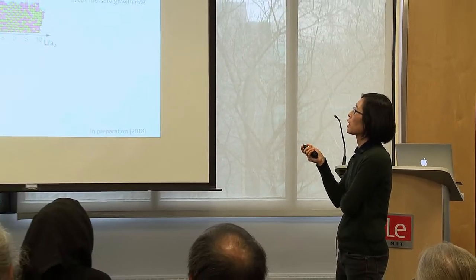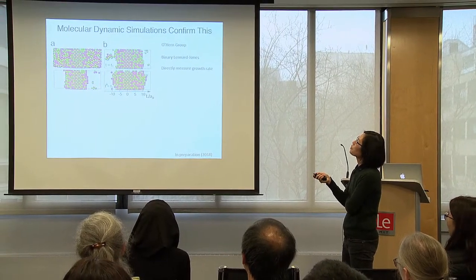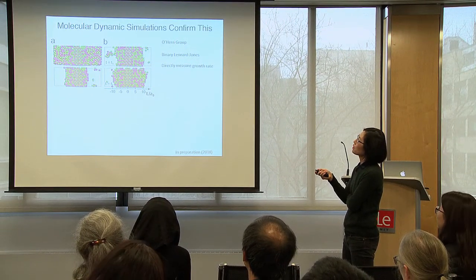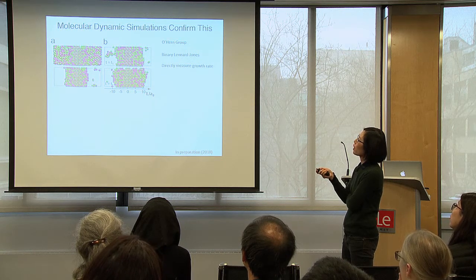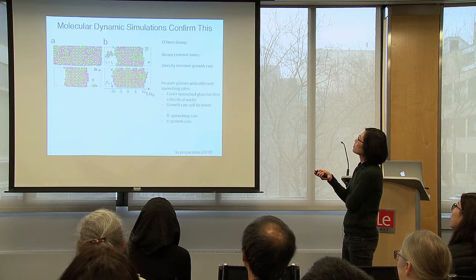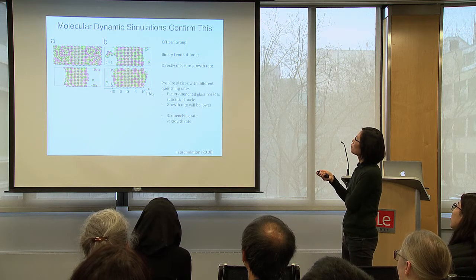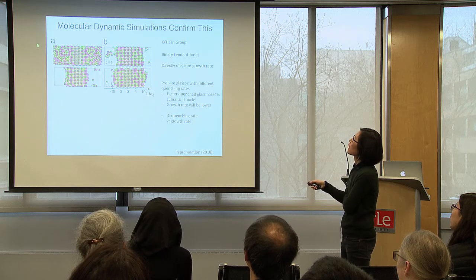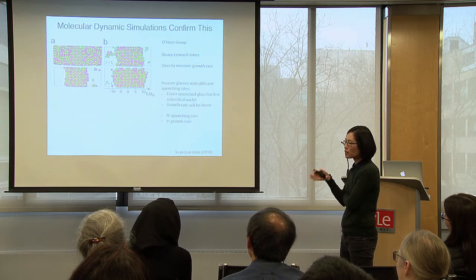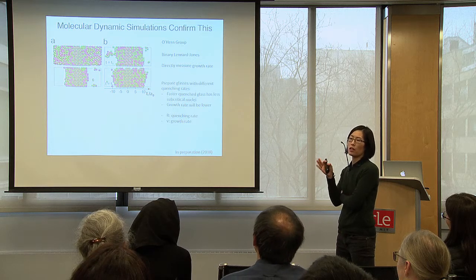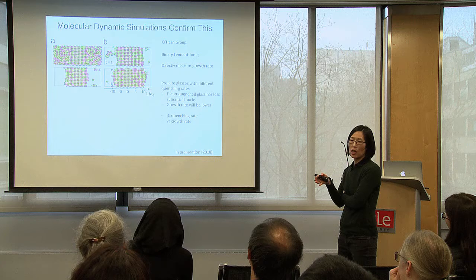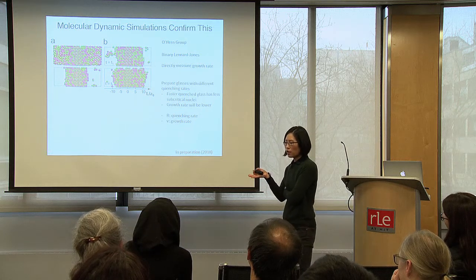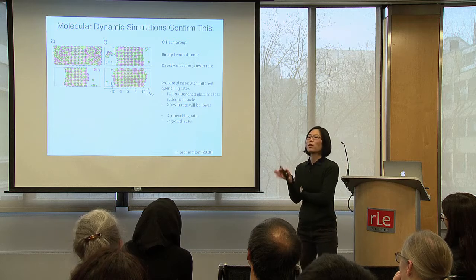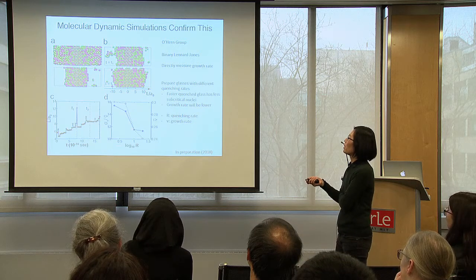Working with Corey O'Hern's group at Yale, we did very simple binary Lennard-Jones molecular dynamics simulations. We kept the middle portion of the rod crystalline, and the two ends amorphous, and we watched the growth dynamics. This is a little bit complicated, but what we did is we varied the quenching rate when we make the glass part here. The idea was that the faster the quenching, the fewer clusters you would have in the glass state. So if the quenching was faster, then the growth rate should be slower because you don't have as many clusters, okay? And that's basically what we saw.